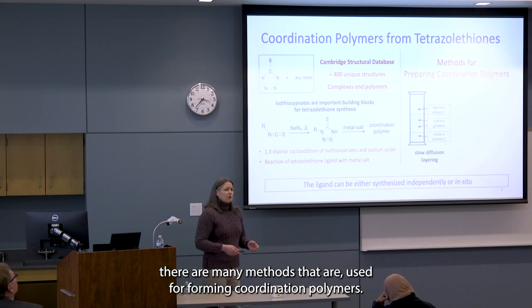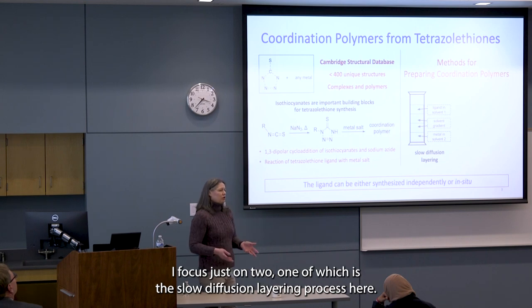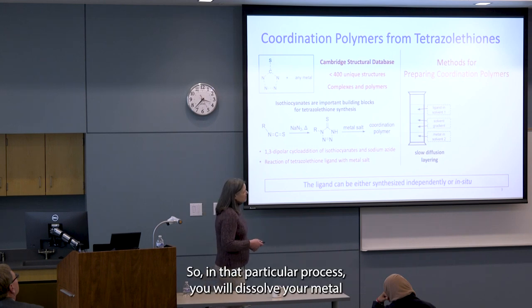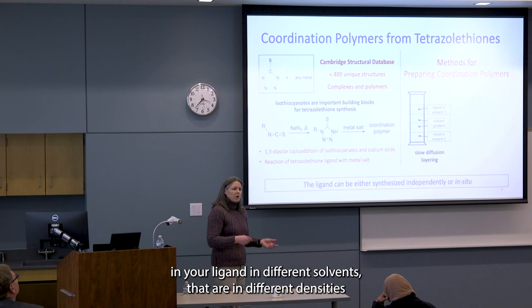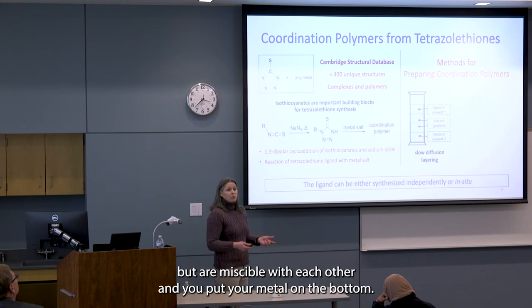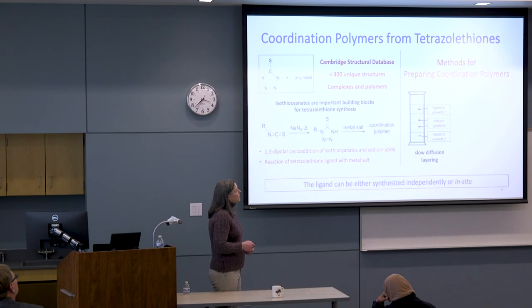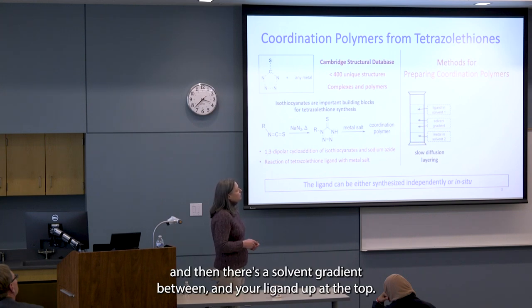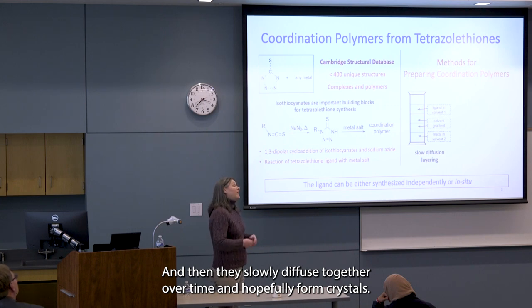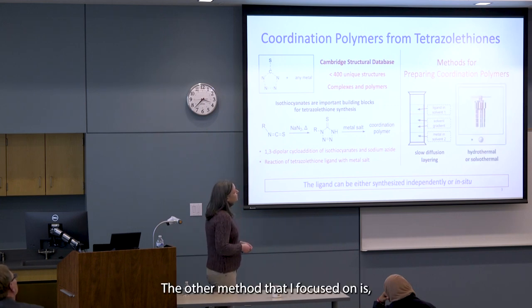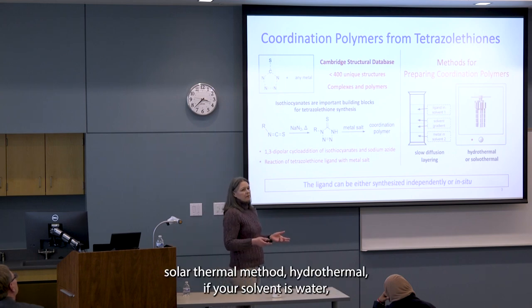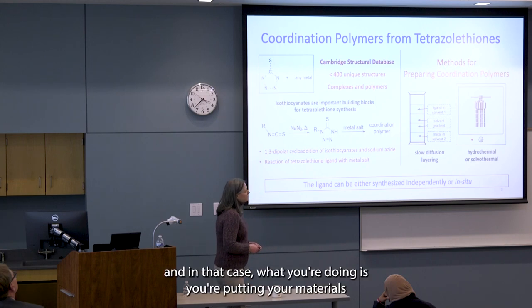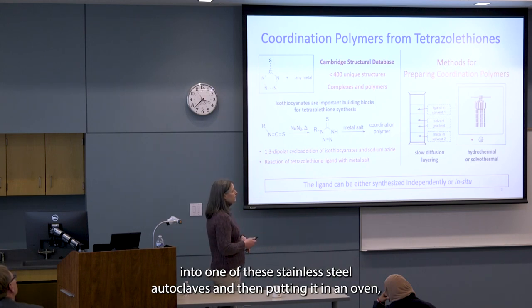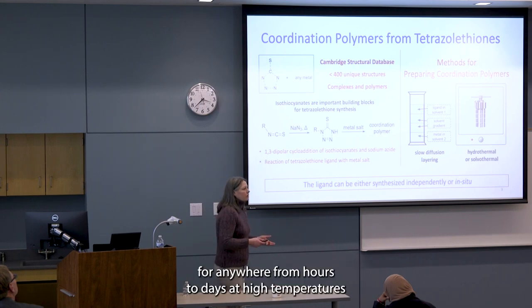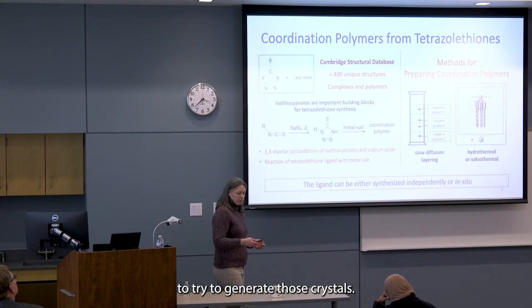There are many methods that are used for forming coordination polymers. I focus just on two, one of which is the slow diffusion layering process here. So in that particular process, you will dissolve your metal and your ligand in different solvents that are different densities but are miscible with each other. And you put your metal on the bottom, and then there's a solvent gradient between it and your ligand up at the top, and then they slowly diffuse together over time and hopefully form crystals. The other method that I focused on is a solvothermal method, hydrothermal if your solvent is water. And in that case, what you're doing is you're putting your materials into one of these stainless steel autoclaves and then putting it in an oven for anywhere from hours to days at high temperatures to try to generate those crystals.